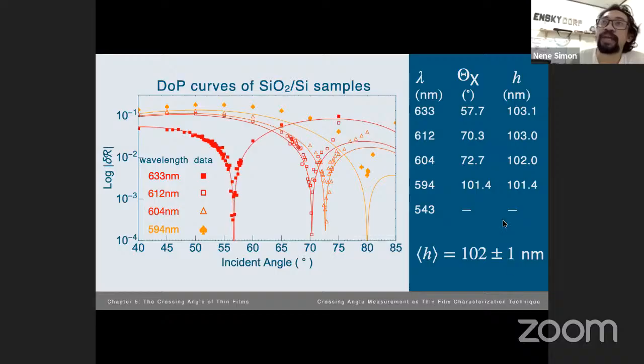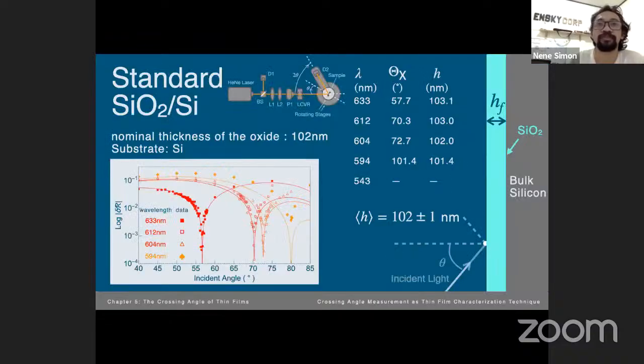So from these values, the measured thickness has an average value of 102 plus minus 1 nanometer. So from here, we can say that our technique can measure with an uncertainty of at least 1 nanometer.